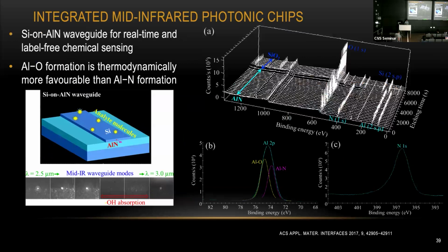So this data was taken a couple of years ago, and we are working on some integrated mid-infrared photonic chips. We need to build some waveguide, the silicon waveguide, on top of aluminum nitride thin film. During the fabrication, we are not expecting anything between the silicon waveguide and the aluminum nitride thin film. But when we do the depth profiling, starting from the top silicon waveguide here, we do see some oxygen between the aluminum nitride and the silicon substrate here. Later we found out there was some kind of impurity oxygen gas during the deposition of the aluminum nitride thin film.